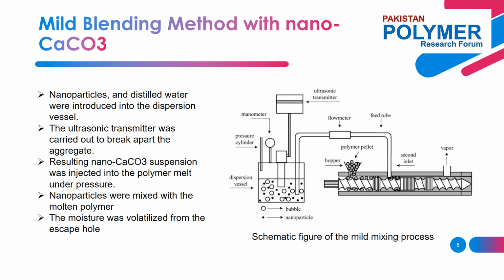Then the resulting nano calcium carbonate suspension was injected into the polymer melt in a co-rotating twin screw extruder under pressure through a feed tube and a second inlet drilled on the barrel of the extruder. The nanoparticles were mixed with the molten polymer and transported ahead. Then the moisture was volatilized from the escape hole, and nanoparticles were held in the matrix at the primary diameter as in the suspension. The extrudate was then pelletized. After drying to remove the attached moisture from the extrusion and pelletizing, the pellets were injected into both dumbbell tensile samples and impact samples.